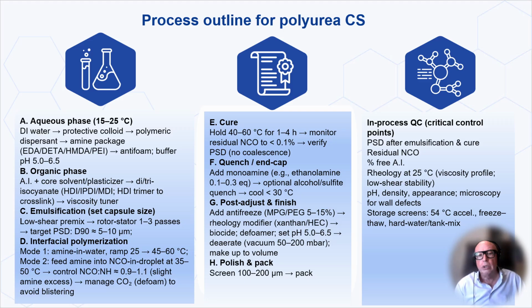Key control points throughout. Monitor pH constantly. Track particle size distribution during emulsification. And most critically, during polymerization, control NCO to NH ratio and temperature ramp while measuring percent-free active ingredient outside the capsules to ensure proper encapsulation efficiency.